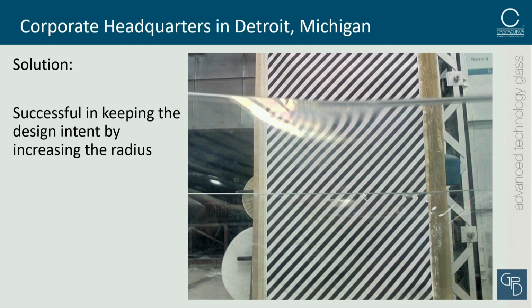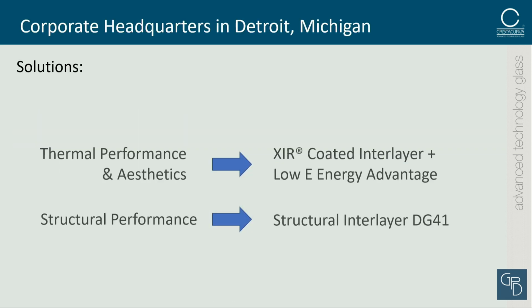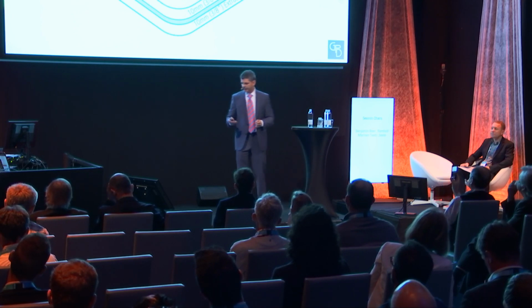So the coatings that we came up with were successful at keeping the design intent. By changing the radius, the design intent stayed the same, and we were also able to accomplish the thermal and the performance aesthetics that they needed using the following products. The first one was an XIR interlayer, and we also used a hard coated low E product as the internal piece of glass. And for the structural performance, we used a DG41 and 2 layers of 10 millimeters glass.